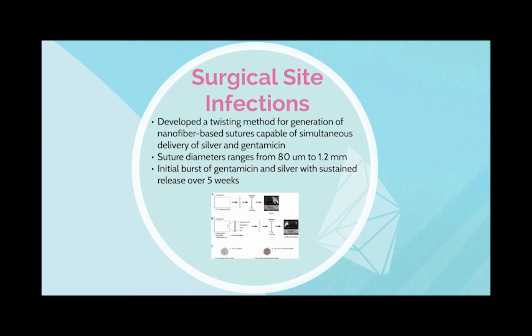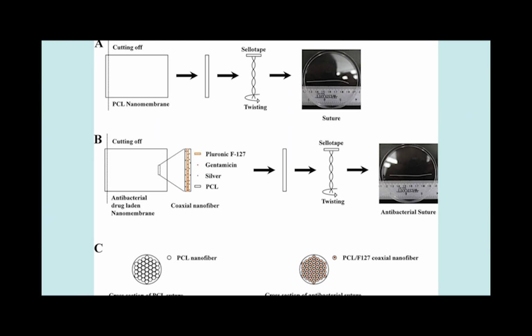In our surgical site infections, we have developed a twisting method for the generation of nanofiber-based sutures, which are capable of simultaneous delivery of silver and gentamicin. Silver and gentamicin both help prevent these surgical site infections. They found that their suture diameters ranged from 80 micrometers to 1.2 millimeters, and that the initial bursts of gentamicin and silver had a sustained release over 5 weeks. This image shows that basically you can twist the fiber and that you can see the difference between the cross-section of their coaxial nanofiber with silver and gentamicin compared to their simple PCL, which is polycaprolactone nanofiber.